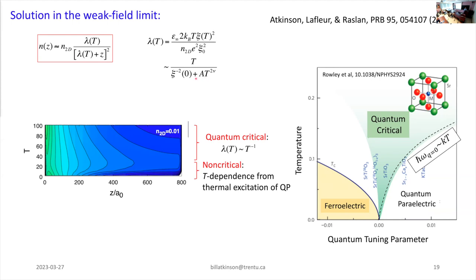It's the temperature at which the second term in the denominator becomes comparable to the first term. When the temperature is much less than this, you can kind of ignore it, and all the temperature dependence comes from the numerator. The crossover happens when the temperature dependence in the denominator becomes big. The 25 Kelvin comes out of the math. I've used parameters for strontium titanate; our model parameters come from fitting susceptibility measurements. We have a big list of papers that we fitted our models to, to find an optimized model that would realistically reproduce the physics of strontium titanate. That's where the 25 Kelvin comes from.